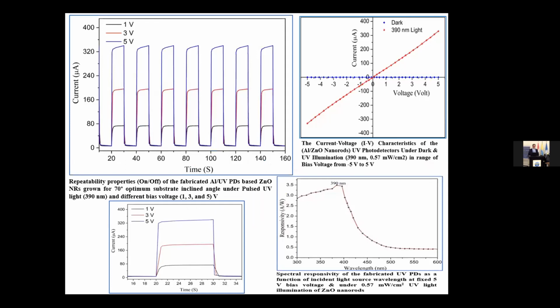This result shows the IV characteristic of the UV photodetector. The IV characteristic of the photodetector of aluminum zinc oxide nanorod under the dark and the illumination of 390 nanometer with the power of 0.57 milliwatt per centimeter square, in the range of the bias voltage from -5 to 5, shows the ohmic behavior. You can see from this figure we have the ohmic behavior.